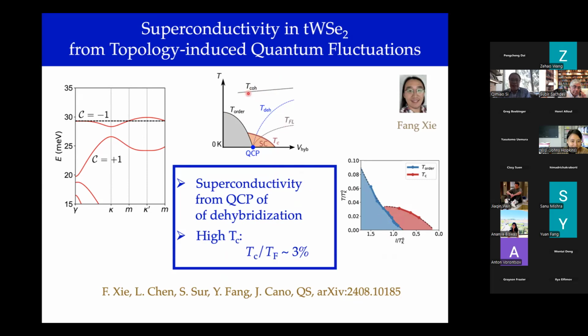So the story about superconductivity in the twisted transition metal dichalcogenides is just the beginning, and I think there's a lot more to come experimentally, and a lot more to consider theoretically as well. But at this point, I want to make the point that the bands in many ways are very clean. We recently looked at the details of the Kagome metals. There are typically 30 bands that are mixed together, and one has to work a bit harder to isolate, in these realistic materials, the molecular orbitals that are appropriate to describe this real space description and incorporate interaction effects.